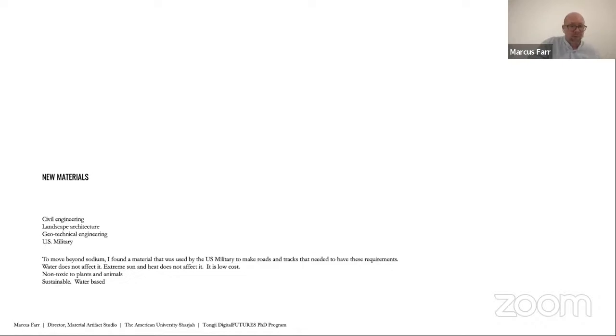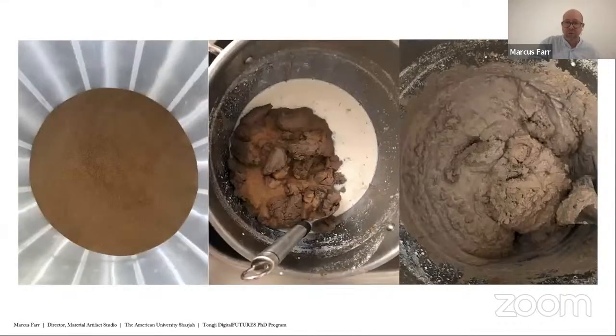And so we looked at some material that's used by the US military to make roads and tracks in tropical locations and extreme climates. This is a low-cost material. It is not affected by the sun. It's also really important in that it's non-toxic to plants and to animals, and it's water-based, which is very different than some other materials that we've used with the sand. And so this is a slump test that we're seeing here. It's normally tested as a spray-on material with road crews to make roads and trails and places for cars to drive on.